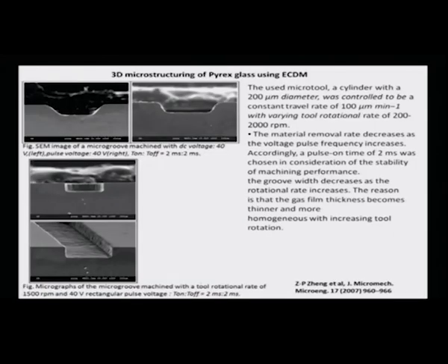There are some other examples of ECDM processes where in Pyrex glass people have used ECDM micro milling. So there is a disc type motion here of a tool which is rotated at a very high RPM, 200 RPM or so, and which creates this electrochemical discharge machining between the substrate and the tool. And in this particular illustration you can see some beautiful SEM images of channels being produced at a pulse on time of roughly about 2 milliseconds, and the tool travels in this case at a constant travel rate of 100 micrometers per minute. So the process is a little slow in terms of the yield of the material removal rate, etc. And the tool used in this case is a cylinder of about 200 micrometer diameter.